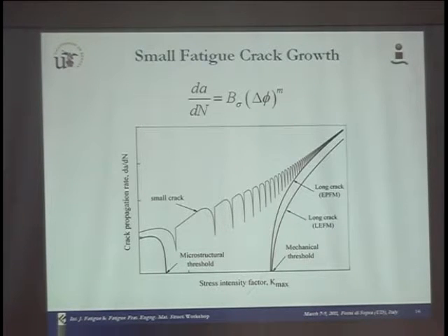So if you use the crack closure concept for long cracks, you are in these two regions: R parameter higher than 0.6, that is residual closure, intrinsic threshold, and R lower than that, you are in a closure range, and you can predict without fitting, since you know the effective range.